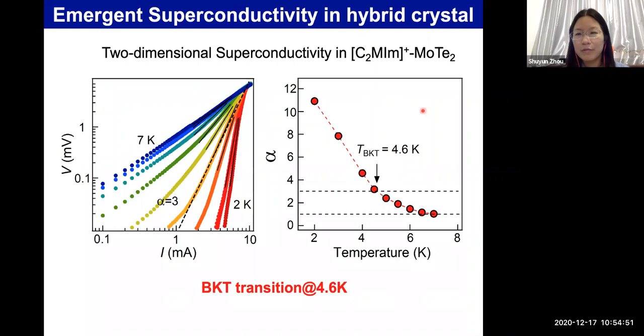So we further look at the superconducting property of this intercalated sample. And here I show you the VI measurement at different temperatures. Near the transition temperature, we can fit the data using a power law behavior, and the extracted exponent is plotted here as a function of temperature. At the exponent alpha equals 3, this gives a BKT transition temperature of 4.6 Kelvin. And this tells us that the superconductivity is behaving two-dimensionally.